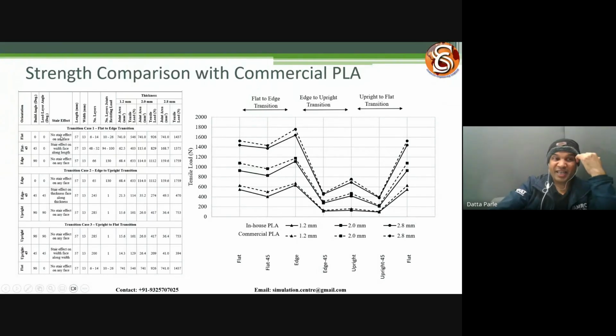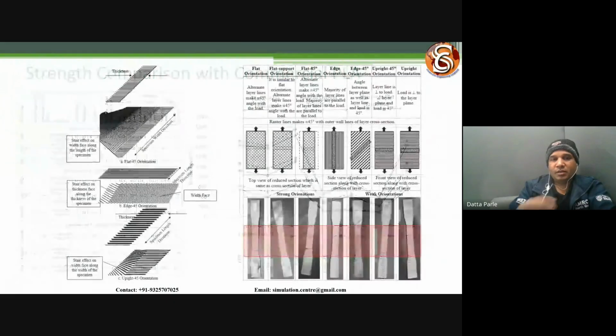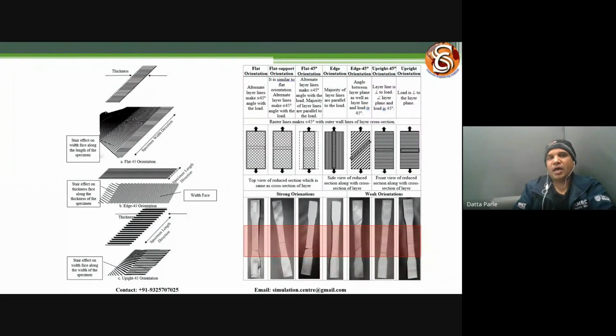We observed there is something called the stair effect, and that became one of the understandings for the future of how the fracture behaves. So the thickness may be 1.2 or 2 or 2.8, and when you are printing in different orientations, if you are flat or edge or upright, probably you don't see the stair effect. But whenever there is an inclined orientation, it played a critical role in the way it fractures.